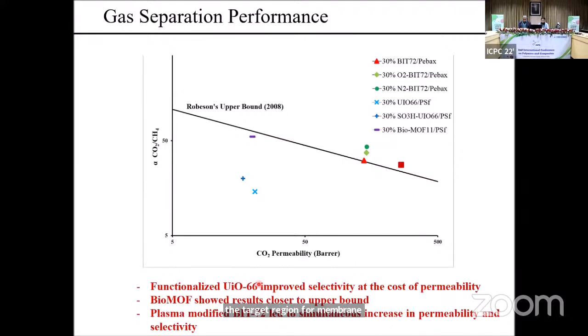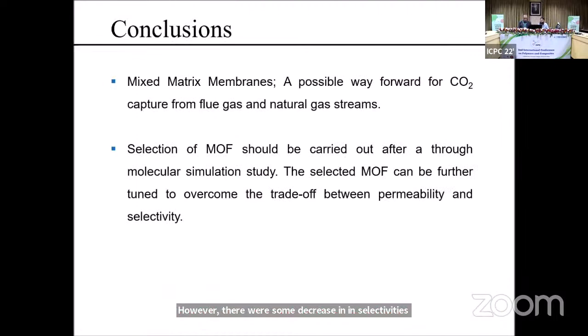The functionalized UIO66 based membranes showed very high selectivity. However, there was some decrease in selectivities, which can be overcome by using the modulation approach. To conclude, we can say that mixed matrix membranes are indeed a way forward for CO2 capture, whether it's post-combustion capture, or whether we want to separate CO2 from natural gas or biogas. However, we cannot simply try just a new MOF and a new material and test its properties for CO2 capture.